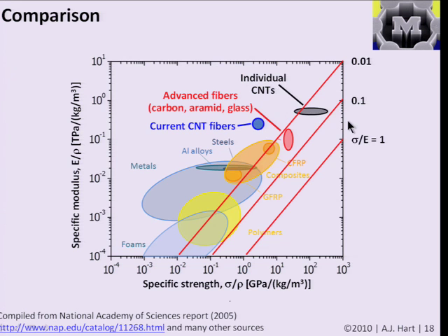axial modulus of graphite. Because of their organization, their microstructure and nanostructure, most bulk materials are beneath this limit. Likewise, fibers made out of nanotubes by putting them together, a topic we'll talk about more later, are even more significantly below this limit than some other bulk materials. Advanced fibers, for example highly engineered polymers where the chains are really well oriented, or where you start with a long-chain polymer, orient it really well, and bake it at high temperatures to convert it to a very high quality graphite, can also get toward this limit.